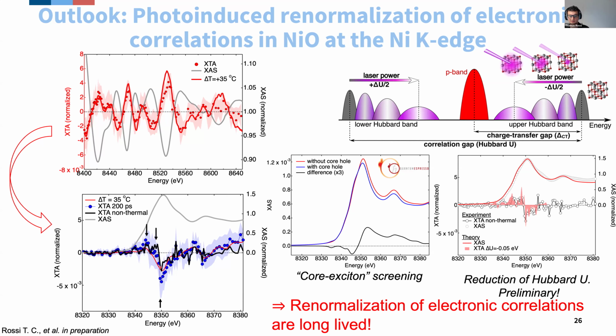And when we tried to explain what was the origin of this non-thermal signal, we first did simulations of the core exciton screening similar to the ones that we did for the zinc oxide, and found out that it was not agreeing very well with the experimental data. But when we did the simulations by renormalizing the correlation gap instead by 50 millielectron volts, that's the red shaded curve. I actually have to apologize that I got corrupted data before this talk, so I'm only able to show you an unconvoluted pump probe signal.